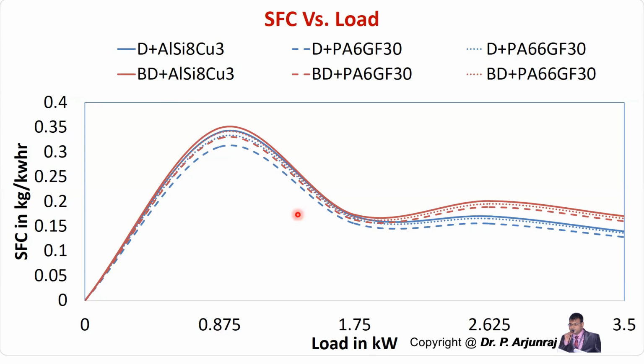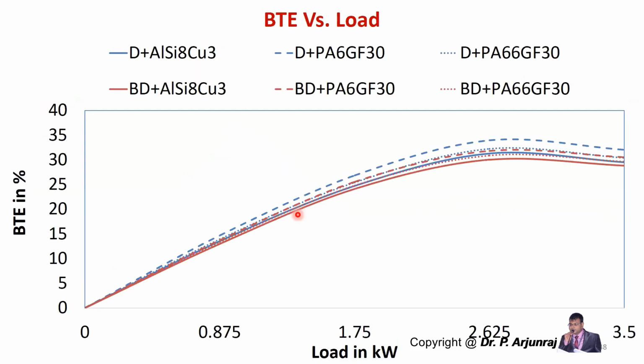And next is going to be the brake thermal efficiency versus load. And here you can see that the PA6 with glass fiber of 30 is having the high brake thermal efficiency when compared to the PA66 and also aluminum. This is because of the incoming air and also the increase in the density. The enhancement in the air density results in the improved air fuel mixing during the combustion. And the graph highlights that the manifold material plays a crucial role in influencing the brake thermal efficiency. And PA6 glass fiber of 30 material is showing the improved brake thermal efficiency for both diesel and also the biodiesel.